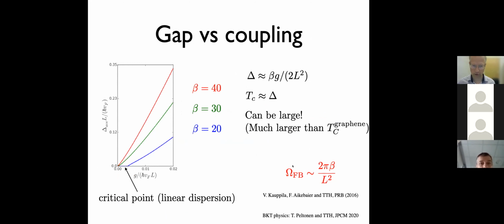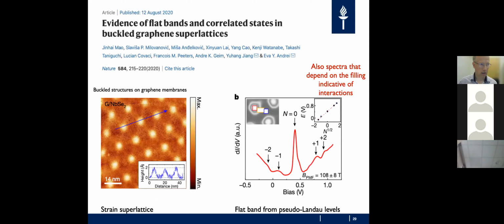In this case, the size of the flat band is slightly different than before, so this is now fixed by the amplitude of the strain and the period of the strain. There is some quite recent work from Eva Andrei's group, where they studied such periodic strain profiles in graphene, on buckled structures on graphene membranes, and so they realized the strain superlattice. What they can see in STM is the presence of Landau levels from this pseudo vector potential. And basically the zeroth order Landau level is the flat band that I mentioned before.